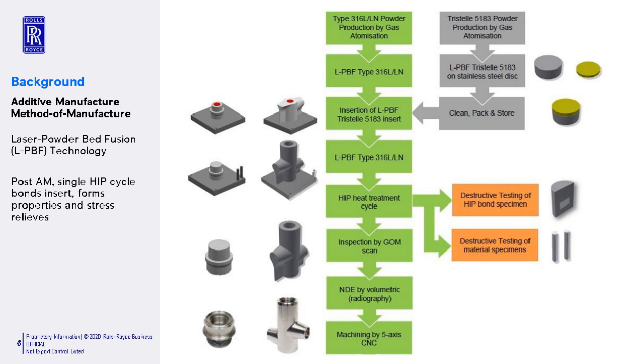We then build the stainless steel body or bonnet component using, again, laser powder bed fusion technology up to a midpoint just above the location of the actual insert. We then pause the build and evacuate the powder from the insert location, leaving an inbuilt recess. We then take the previously produced Tristelle insert and position it in the build with the stainless steel disc uppermost. We then continue the build process over the insert, encapsulating it in position until the final near-net shape valve body or bonnet component is formed.